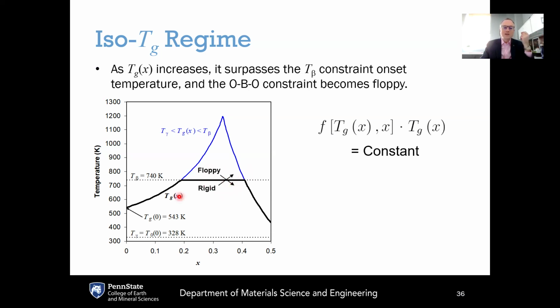And the result is that if this Tg curve tries to cross T beta, it basically gets stuck there at exactly equal to T beta, because every time it goes above T beta, those constraints become floppy and it wants to drive the Tg back down. But when it goes back down, those constraints become rigid and wants to drive the Tg back up.